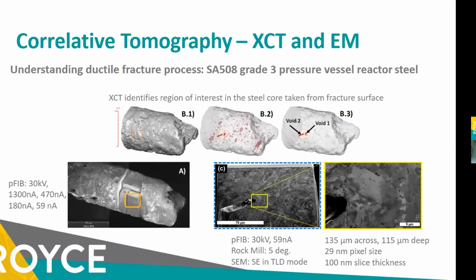We can use these 3D images to find regions of interest. For this particular example, we can see the voids that form during failure with XCT. This provides us with really useful information. But we want to look further, zoom in and understand more about the microstructure around the voids, for example. These voids are air holes, and X-ray computed tomography shows the hole and the metal. When we go down in length scale with the plasma FIB that we've got, we're able to see these smaller voids because this is a much higher resolution technique. And so we can see the microstructure around the voids that we were looking for.